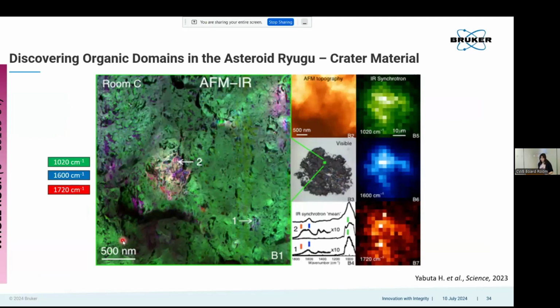But when we look at that, we see something that's really, really impressive. So these materials are based in two different categories. One are the crater materials and one are the surface materials. So this one has a defined code associated with it that you know is from the crater in particular. And what they did is they sectioned these really thin.